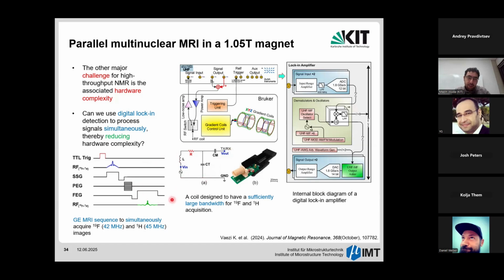For the imaging sequence, we used a gradient echo sequence, where we also added a TTL trigger signal so that we can synchronize the two systems. For the RF excitation, we used one single excitation pulse that has two RF profiles to do slice selective excitation of both nuclei. When we acquire, the signal is a combination of two FIDs of the two nuclei that can be separated digitally in the lock-in amplifier. Of course, we needed to modify the detector, so there are two options. Either we make the coil a double resonant coil, or because the frequencies were quite close to each other, we're talking about 42 and 45 megahertz, we thought it would be easier to just increase the bandwidth of the coil by artificially lowering the Q factor of the coil.